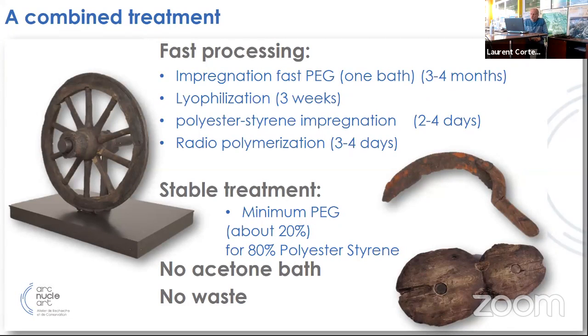This new combined treatment is very convenient. It is fast. It lasts something like 6 months, no more. Stable, because very little PEG. There are no acetone baths, no waste, because we can reuse both PEG and resin that are not mixed with other products. And the parts that are not impregnated can be reused. So it is really convenient.